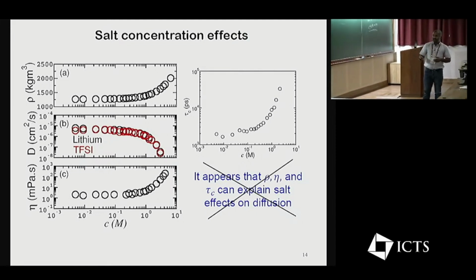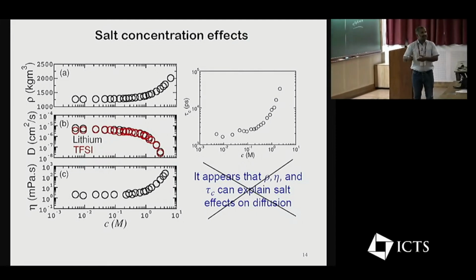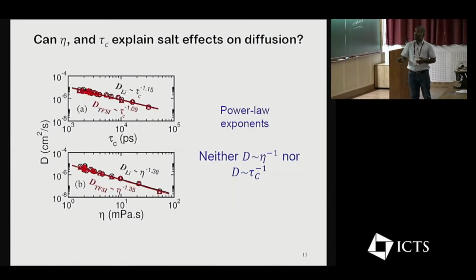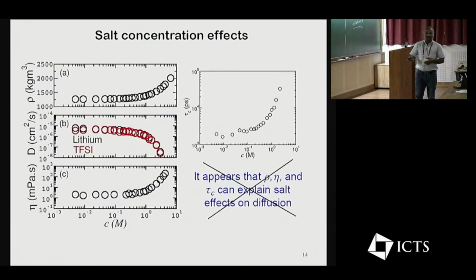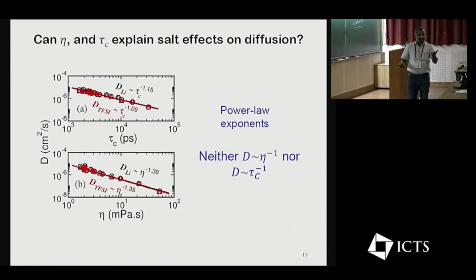the exponential decay of the diffusion coefficient can be explained qualitatively, of course, but when you look at the quantitative scaling relations, they are not. So there is some deviation from the power law of Stokes-Einstein, whatever is dictated for the diffusion coefficient.